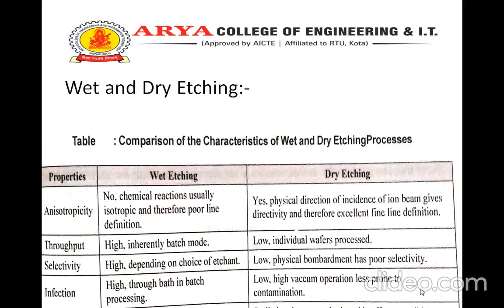Consider, for example, the case of etching of silicon using a mixture of HF (hydrofluoric acid) and HNO3, with acetic acid or NH4F acting as a moderator to control the pH of the etching solution. The HNO3 acts as an oxidizing agent which reacts with the silicon to form its oxide. The oxide is then etched by the HF. If HNO3 is in excess, the oxidation rate is limited by the diffusion of the oxidant species through the oxide, analogous to the thermal oxidation model. In the converse case, the etch rate of the oxide determines the overall etch rate.